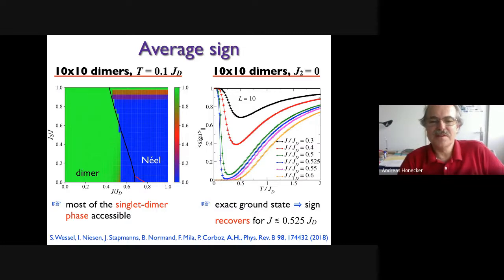There's a drop as you come from high temperature that is more severe if you go to a stronger coupling between the dimers. But if the coupling is not too strong, the sign recovers at low temperature. For example, if you see the black curve, the sign is not strictly 1, but it's good enough to work with, definitely. And the only thing is that if you crank up the interdimer coupling too much, the sign doesn't recover at low temperatures any longer.